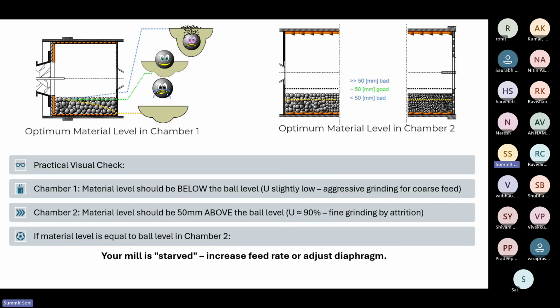Now, optimum material level in chamber one and chamber two. This is a parameter which gives you a first-hand review of the mill just by looking at it. The minute you enter the first chamber, if you can see all the balls, 90% of your top balls are visible, and there's not a lot of material next to the diaphragm, it's obviously not in a very good state of grinding. In juxtaposition, if the balls are completely covered, you can't see a single ball and there's a lot of material in the mill, that's also not a good case, because then your mill is not grinding. It's being suffocated.